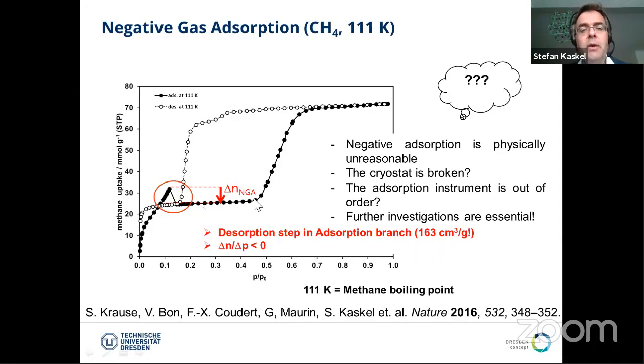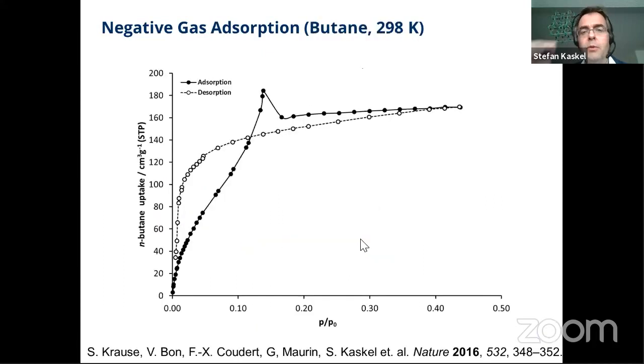And then there's this strange isotherm behavior. There's a huge uptake again here. This is 70 millimole. This is a huge uptake. And then there's this strange hysteresis. So at that time, we didn't really understand that. But my student had a clever idea. So first of all, methane at 111 Kelvin is quite exotic. But we found that this behavior can also be seen at room temperature with other gases. For example, butane has a higher heat of adsorption and it shows a similar behavior at room temperature. And it also has a kink here in the isotherm and then a plateau.